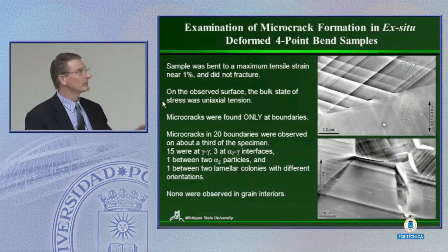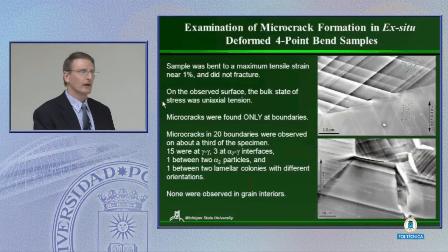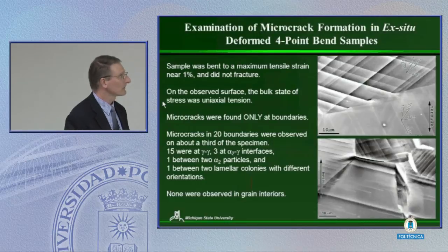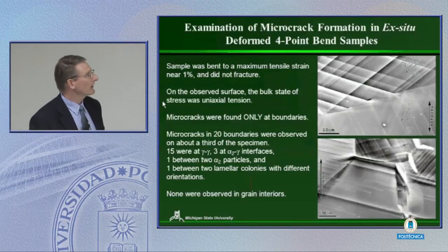So what we've done now is, instead of looking at that side of a sample, 4-point bending, we've gone and looked at the tensile surface of these 4-point bend specimens. And what we find is there's actually quite a few places in here where we get these sorts of cracks nucleating at these boundaries. And so this is a little bit of a complex microstructure. It's not just pure gamma.